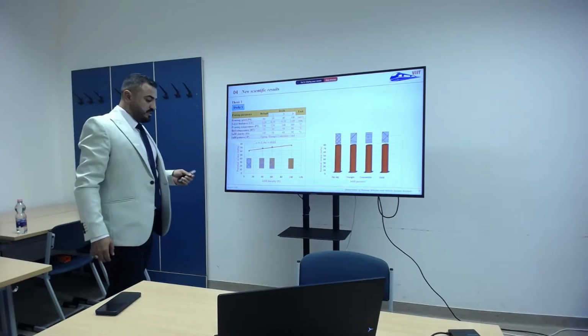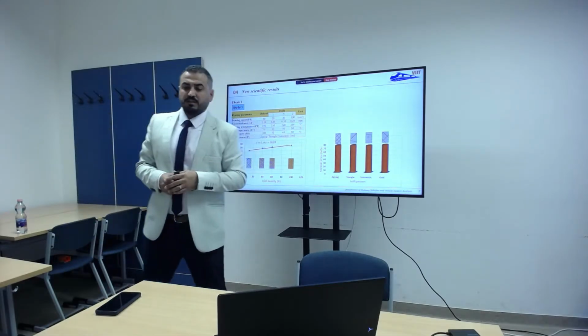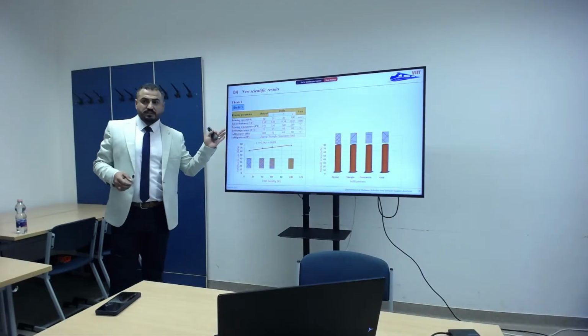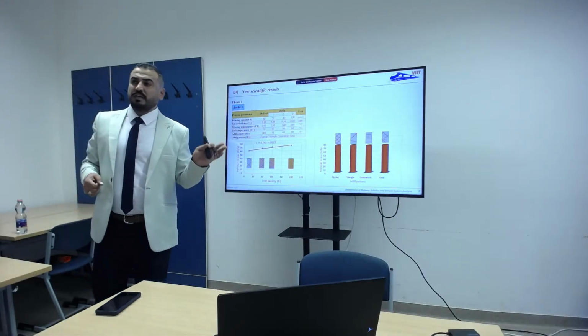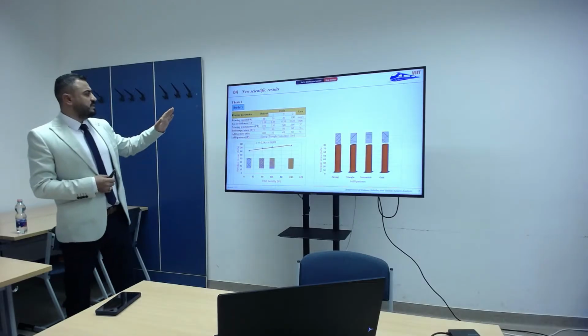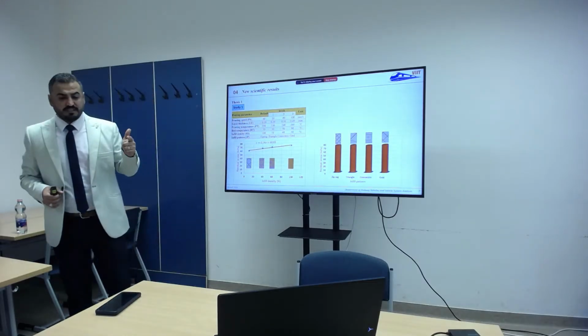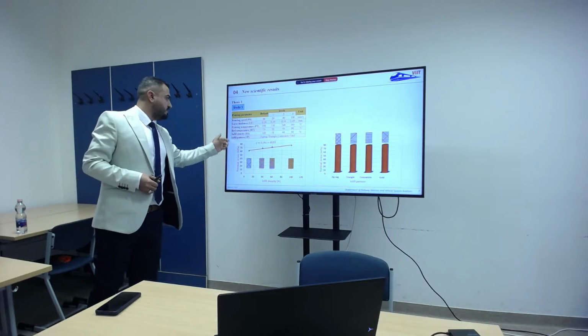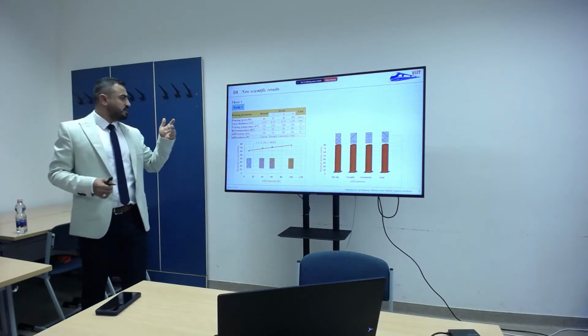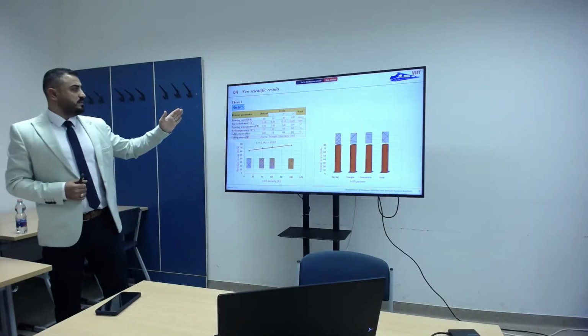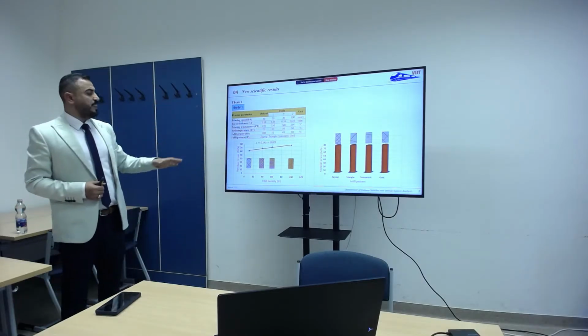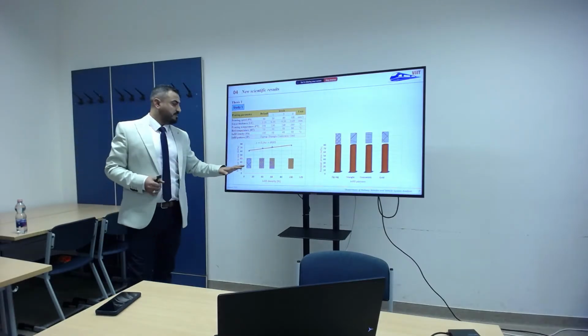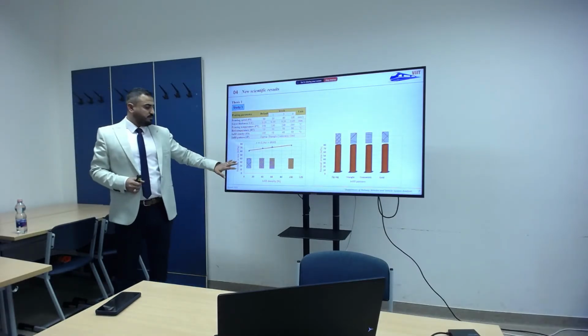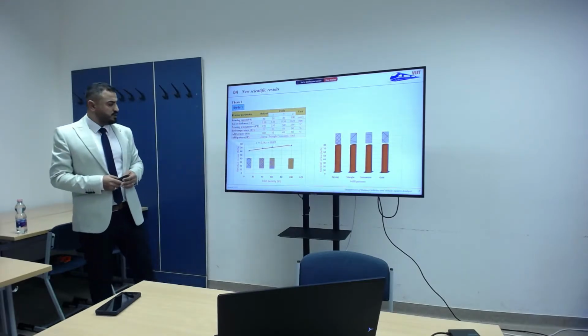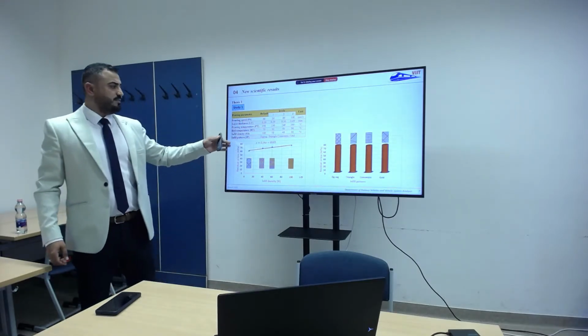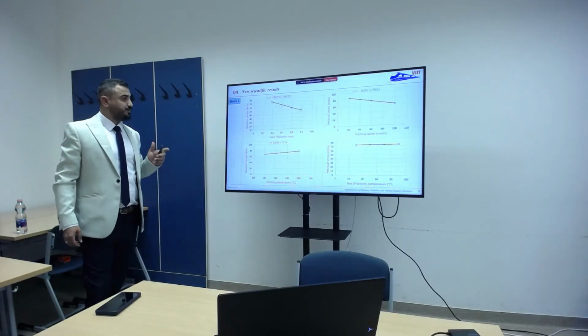For the first thesis point, I made 3 different studies to study the parameters. The first study focused on 2 structural parameters and 4 manufacturing parameters. The structural parameters were the infill density and infill pattern, and the manufacturing parameters were layer thickness, printing temperature, bed temperature, and printing speed. I studied 3 different levels for each parameter, and the results showed that for the structural parameters, there is a slightly positive correlation between the infill density and the residual stress, while the infill pattern does not have any significant impact on the residual stress value.